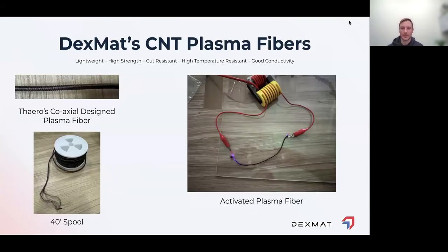So working with them, we were able to transition this plasma fabric to something that was not just parallel or a sheet form. We were able to make this coaxial design. We had this design in our heads, but we just didn't know exactly how we were going to integrate it. But being able to work with them and introduce the Galvorn, which is not only flexible but actually conductive, we're able to make an activated plasma fiber with this technology. By introducing Galvorn, we were able to make everything lightweight. It had a much higher strength than the copper. It's also cut resistant